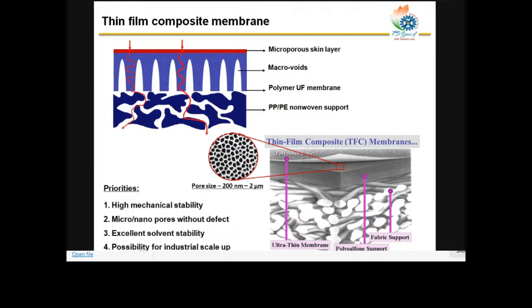And on the right corner, you can see that this is an SEM image, where the fabric is in the lower part, and in between you have a support membrane, which is called the ultrafiltration support, and a very thin TFC or thin film composite layer is on the top. It's made out of a polyamide layer. So to make a thin film composite membrane, you basically need a three layer structure. The lower layer will give the strength of the membrane, and the second layer will give the support for the top layer, because the top layer is very thin. So you have to have a support to hold the top layer.